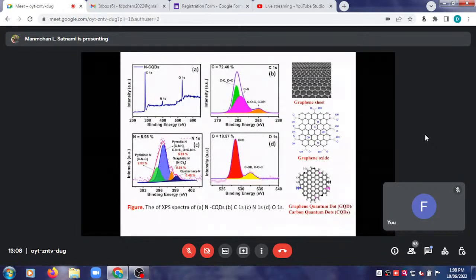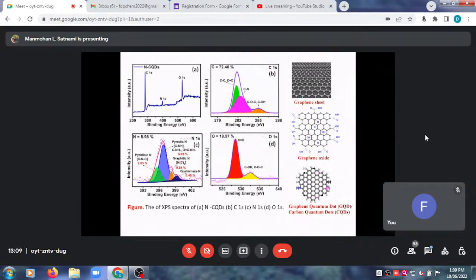And the X-ray photoelectron spectroscopic technique is used to study the binding energy of core electrons. Okay, so what is this XPS actually? This XPS is for the binding energy of core electrons of carbon, nitrogen, and oxygen present in the carbon quantum dot, because nitrogen-doped carbon quantum dot comprises nitrogen, carbon, oxygen, and hydrogen. But hydrogen cannot be detected with XPS, so there is no spectra of hydrogen.